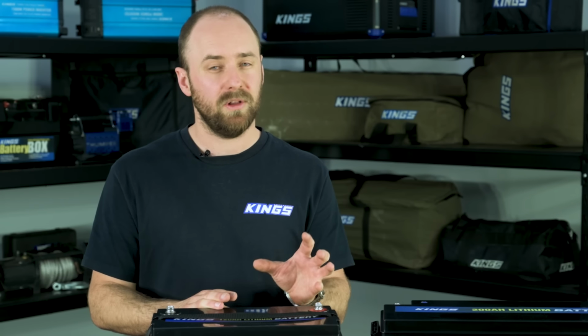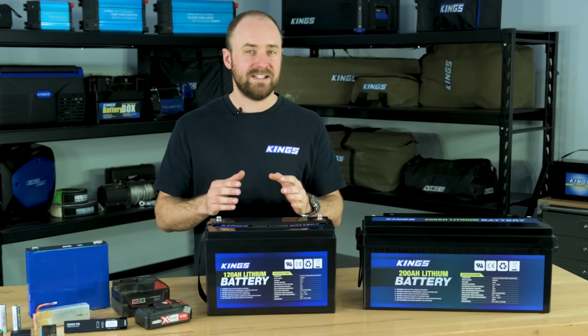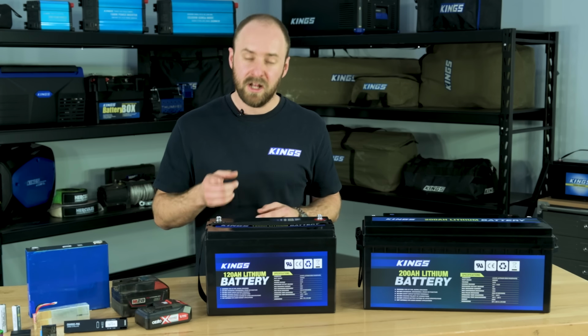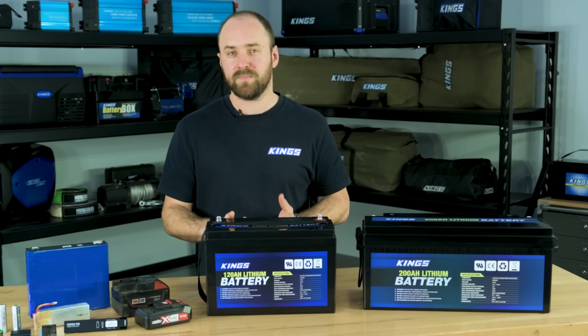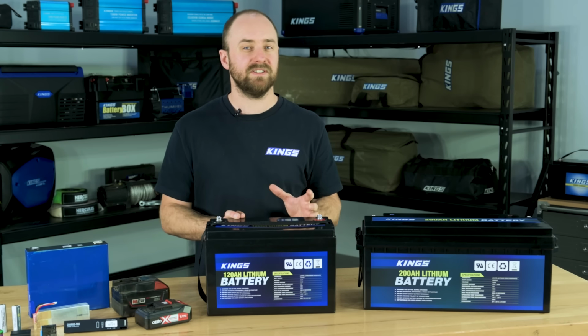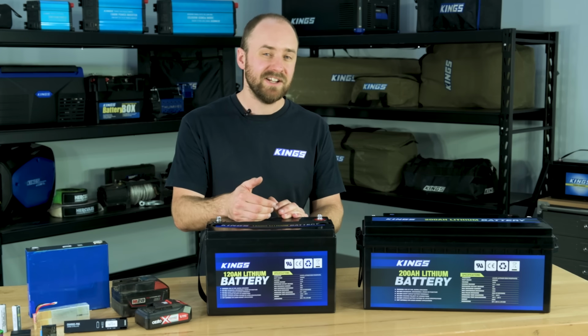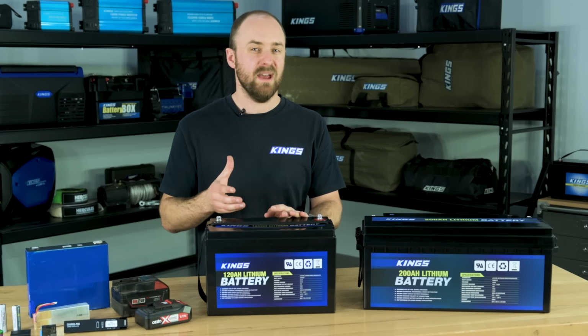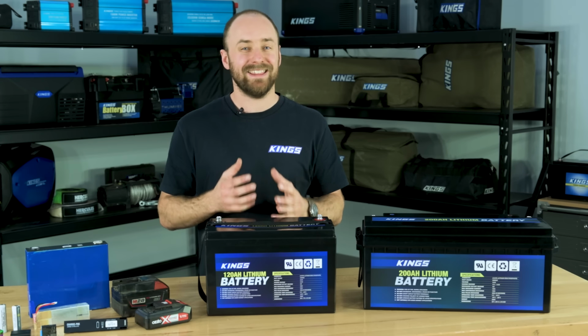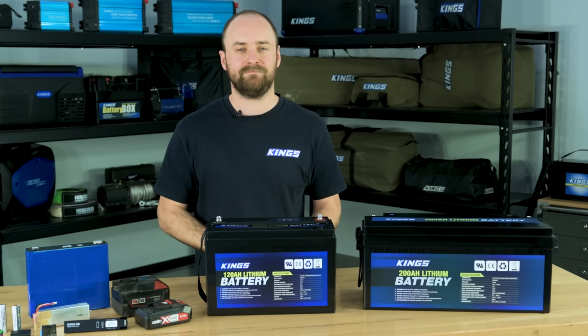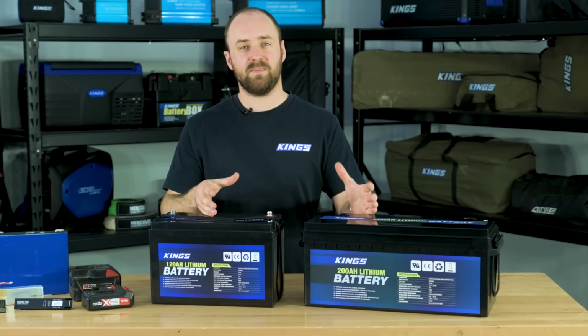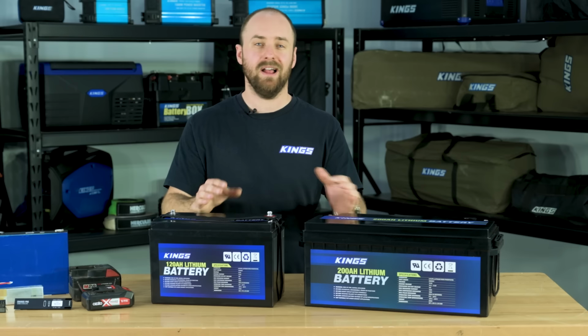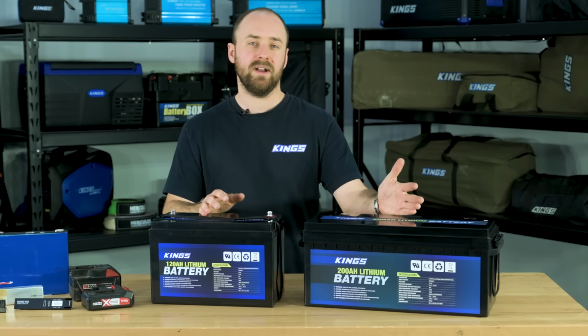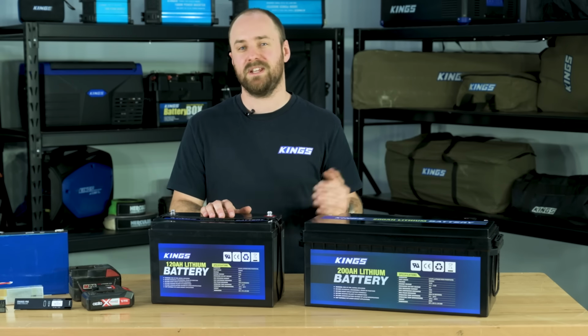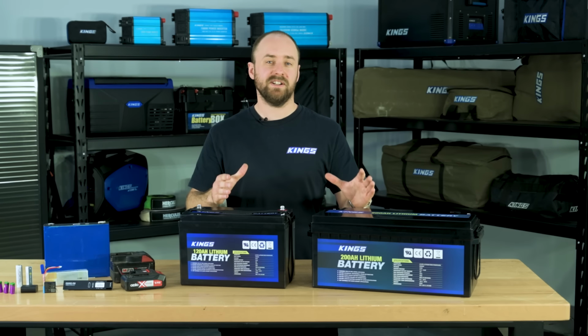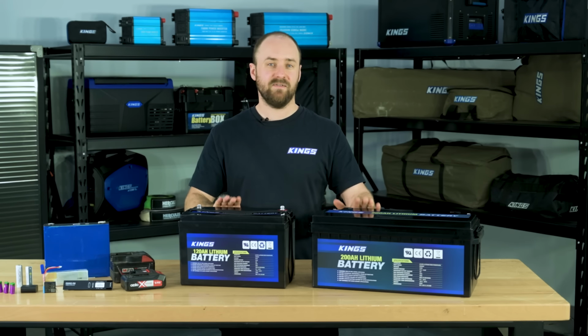It may be a lower quality or lower rated unit, and that could be to disguise a couple of things. For example, lower quality, lower output cells, or the fact that the BMS may not have all the functions it should, and by limiting that input charging current, the batteries are never going to get hot enough to get damaged, so why do you need a temperature sensor? At the end of the day though, it's probably just cost cutting. In these King's batteries, they have a high quality BMS, and you know that because the 120 amp hour allows for 100 amps input output, and the 200 amp lithium iron phosphate allows for 150 amps input output. And they have those critical functions that are necessary to keep these batteries safe and healthy.